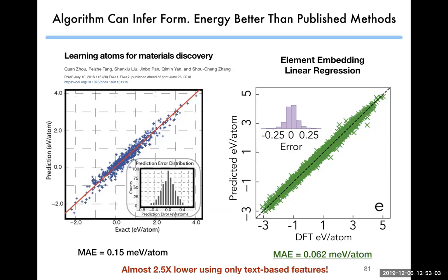So what we did is we used the exact same method as them for creating a neural network to predict the formation energy, but we just gave it the embeddings of the elements from our text model. So it learned these representations from just the text and the way elements are used. And we actually improve on their prediction error for formation energy just from composition for elpasolite structures. So you just take A, B, C, D elements with the specific stoichiometry, concatenate those embeddings together and then feed that to a very simple neural network, and it predicts the formation energy. So we use the same model as them, but our embeddings seem to contain more useful features to make that prediction.